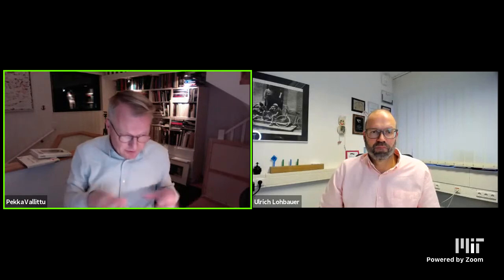Can you see an analog from an engineering perspective of this kind of structure, what we are building in the best case with good adhesive interfaces to both sides, with the glass plates which are used in car windscreens, for instance? And if so, what is then going to be the role of thicknesses of these layers? In window glass or safety glass, you have quite thin layers of glass adhered together. But in our restoration, we can have quite a thick glass ceramic layer underneath. We may have, in the best case, mounting.